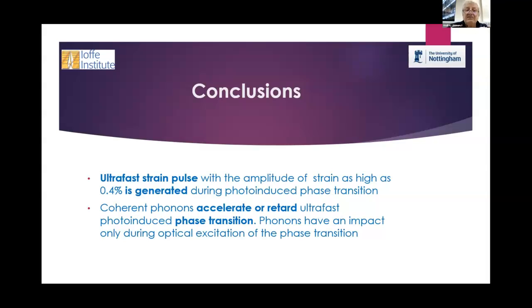this strain pulse is high amplitude and the system is not heated. The temperature does not rise in these experiments. The coherent phonons may accelerate or retard ultrafast phase transition, and phonons have an impact only during optical excitation of the phase transition. Thank you very much for your attention.